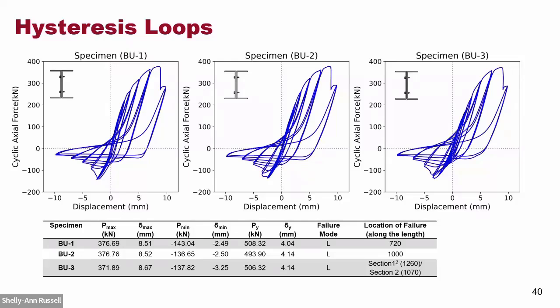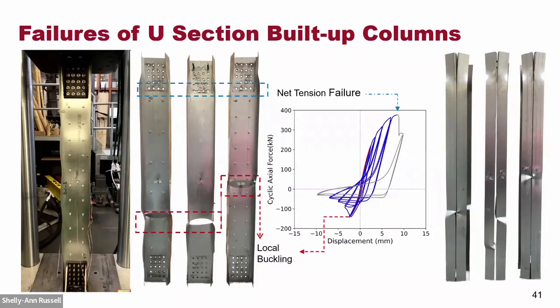So by looking at the same area and same length of the members, you can see the energy dissipation capacity of these U section specimens. One specimen was not joined by the fasteners, and in the experiment they behaved separately, and the damage happened at different locations in these specimens, and the failure mode was local buckling. So you can see the failure mode of U sections. The same thing, you can see the buckling at the web. And after this local buckling damage happens at these webs, the stiffness suddenly decreases. And we have this point again, net tension failure in this net section. And you can see the tearing of these flanges around here.